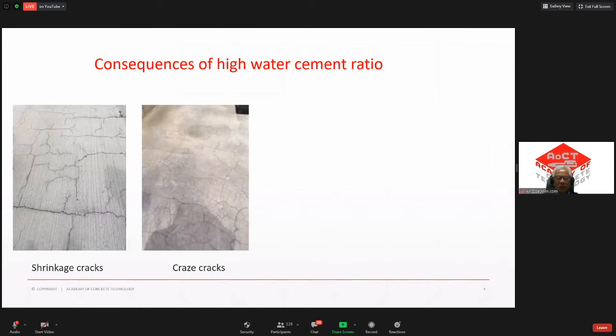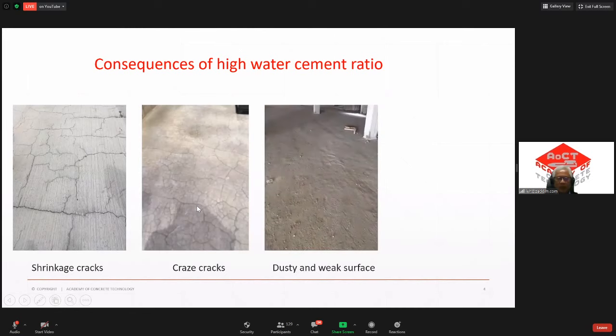You see a lot of spider cracks on the surface, all right? And this is not so much caused by the water, but because when it's so wet, most of the time the workers have to sprinkle cement on the surface, all right? One way of sprinkling the cement is to suck up the water so they can go in and finish off the job early. So when you have too thick a paste, and due to the difference of drying or the temperature, the skin or the surface will always dry up much faster than within. As a result, it's due to the differential of shrinkage. That's why you have a lot of these cracks on the surface. But all these are not actually, I would say, structural, it's just aesthetic. It doesn't look good, but it will never actually peel or delaminate. Okay, it's just unsightly.